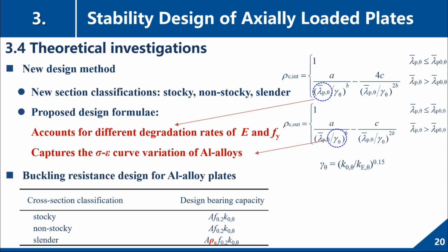So it's essential to propose a new model for the plate buckling resistance. So we proposed new equations based on the European code system. And for our formula, we incorporate two new parameters, which are lambda p theta and gamma theta. The first one accounts for different degradation rates of E and Fy, and the second one captures the stress strain curve variation of aluminum alloys.